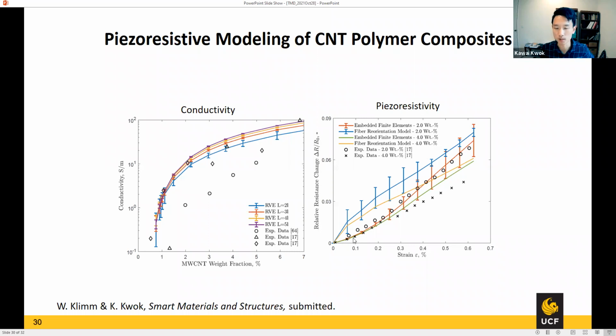What we realize is that if you assume that the CNT is rigid, you would not get the right shape of the curve. That is the case with the fiber reorientation model, where you assume the CNT is rigid and does not change at all in length. You're going to get a very different shape and an over-prediction at small strains.